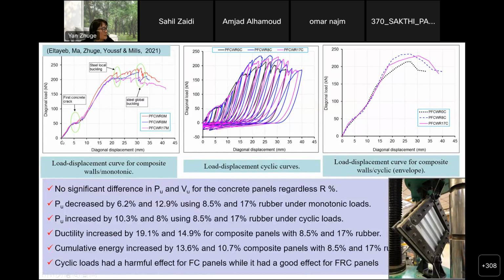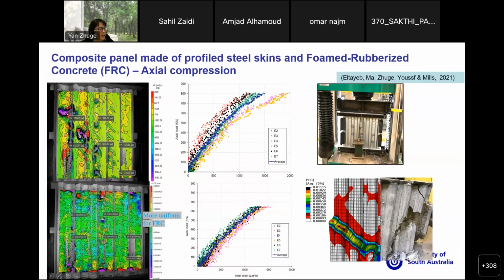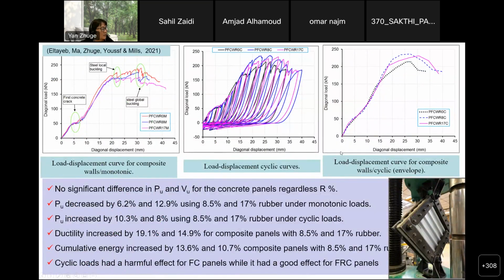Further testing was very interesting. That was the shear test. After we did the axial compression test, we did a shear test as well. From the shear test results, we found there's no significant difference in ultimate load capacity and shear capacity for the concrete panel, no matter what percentage of crumb rubber was used.